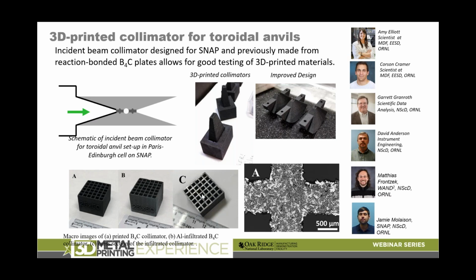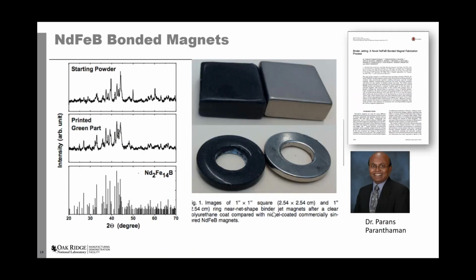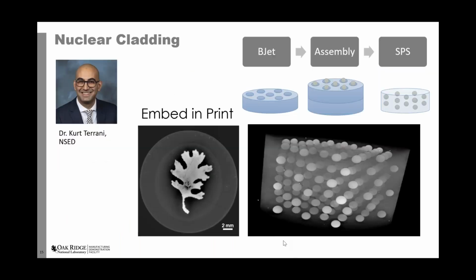But we've also experimented with infiltrating that boron carbide with aluminum to make this metal matrix composite, as you can see here. We've also worked a lot on magnetics, so printing magnetic material and then plating that, and then studying the magnetic effects. Rare earth magnets and magnets in general, when they have to be machined, there's a lot of waste associated with that. It's not always recyclable. So being able to print magnets potentially could save a lot of those materials.